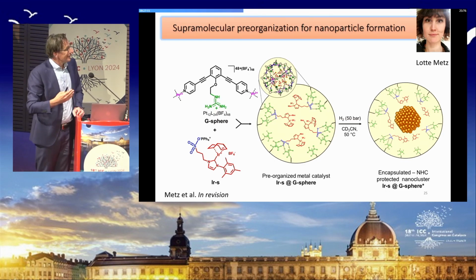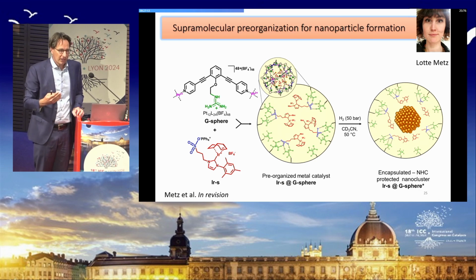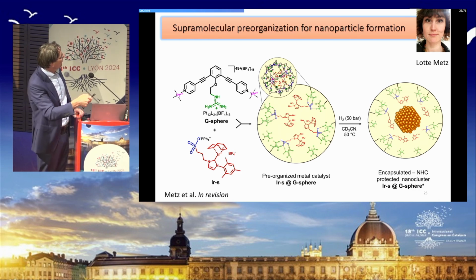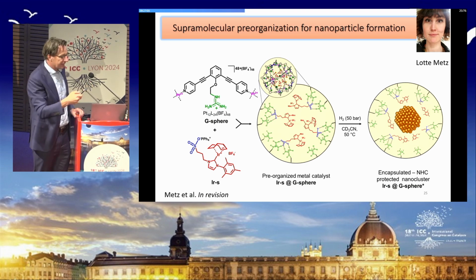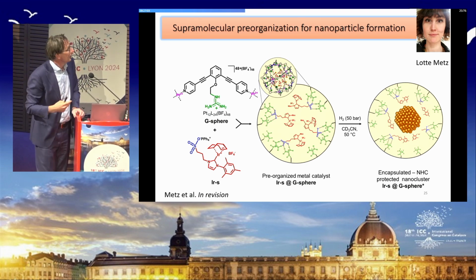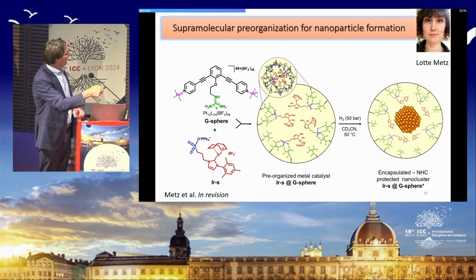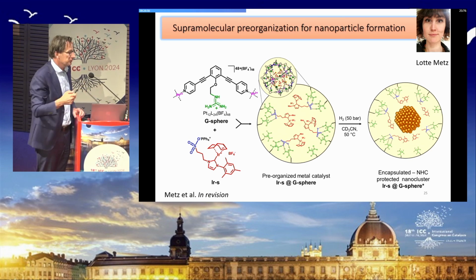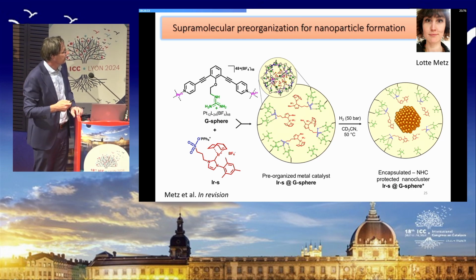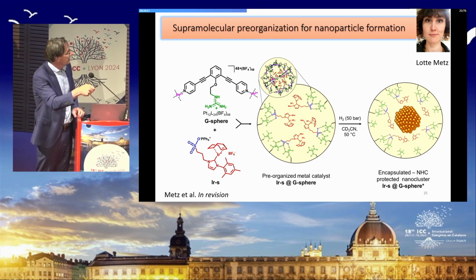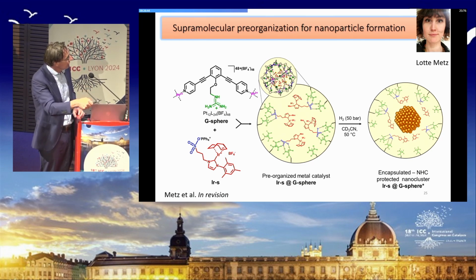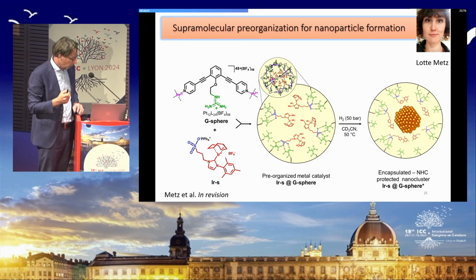So then next we went to the supramolecular pre-organization approach to form nanoparticles. And again, we used our guanidinium-based cage based on platinum that we can fully characterize, so we know what we are having, and then we combine that with iridium complexes that can be organized by sulfonate binding, as previously demonstrated. So we can upload these iridium complexes, and then under mild hydrogen conditions at 50 degrees, we reduce the iridium complex and then locally form the nanoparticle within the cage.